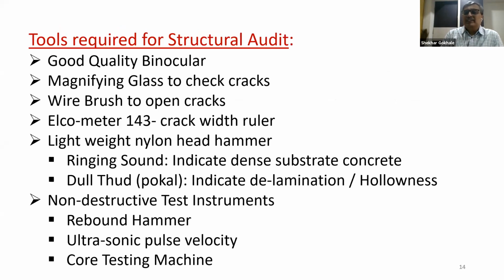Tools required for the structural audit: generally a good binocular, then a magnifying glass to check the cracks, a wire brush to open the cracks, Elcometer 143, that is a crack width ruler, and a lightweight nylon head hammer, where we tap the RCC columns, beams and slabs. A ringing sound indicates the substrate is sound. A dull thud or pokal indicates a delamination or hollowness. By the nylon hammer also, we can understand the overall condition of the building.